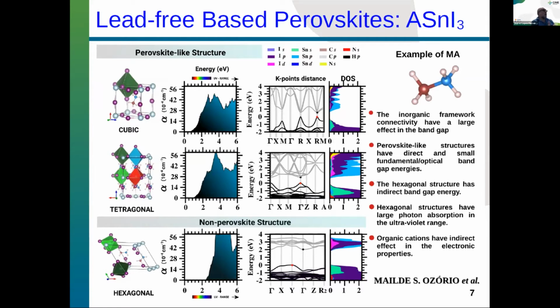We perform those calculations to investigate. What we try to do is make an absorption decomposition to see what part of the crystal really makes a contribution. And here it comes out, as in different systems too, that the inorganic octahedron really plays an important role. The different orientations of the organic cations are important for the stability as a dipole moment orientation. However, the absorption coefficient is not strongly affected by that. However, the distortion of the octahedrons is. And this is what I want you, everyone, to keep in mind after finishing this talk.